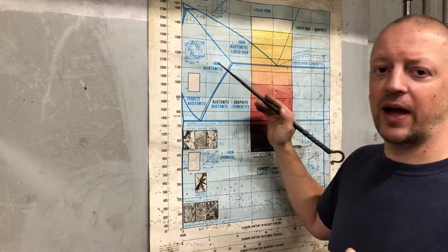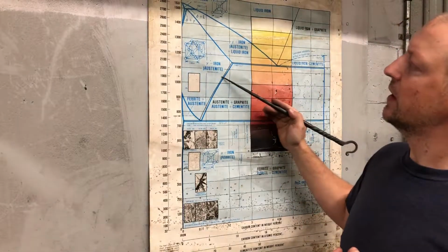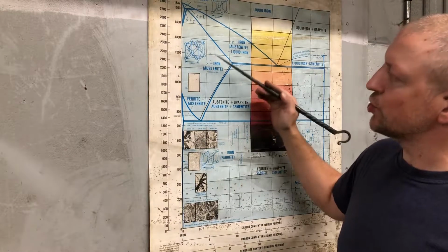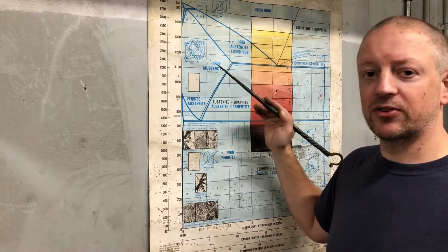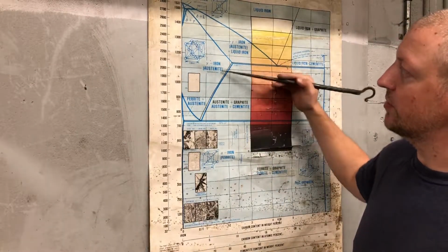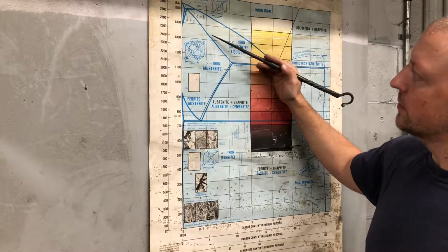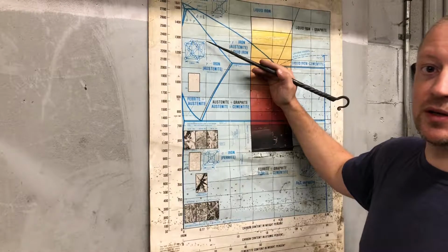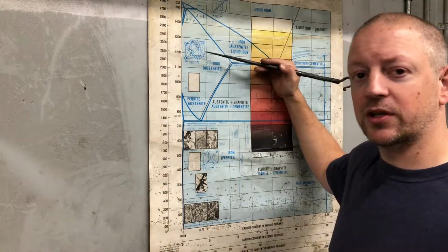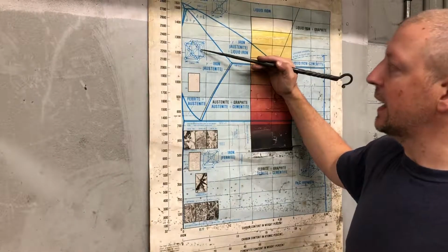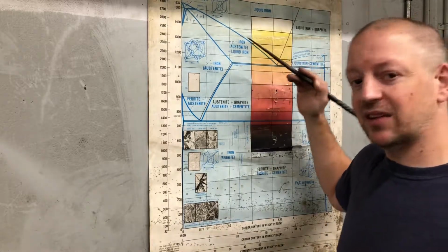Just as soon as you have all that chromium carbide that is very stable at temperature, this pure austenite section shrinks in so much. It's really hard to get full austenite. And the crazy part is that it shrinks in from all directions because the liquid iron side also comes in somewhat. So you run into a situation where you're trying to hit full solution on your carbide and you go a little too far, you bump over into partial liquid. That's not where you want to be quenching